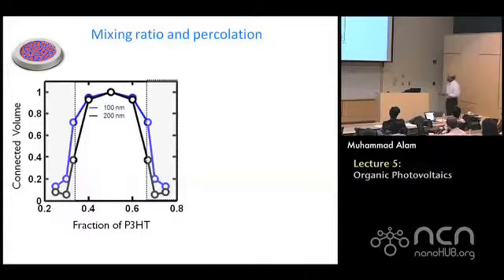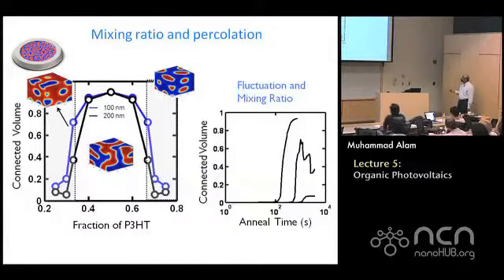And since in 3D the percolation threshold is 33%, at 33% they begin to percolate, it will turn out that close to 33%, the efficiency of the connected volume begins to fall very, very rapidly. So you cannot really go away from 1:1. There's no way the connected volume will arise. So in one condition, all the blue will be trapped within this red, and they can dissociate the exciton. They are not going to contribute to current. In the other condition, the red will be trapped in the blue, and again, you have no current. And in between, you have a connected volume. Both electrons and holes are coming out from their respective contacts.